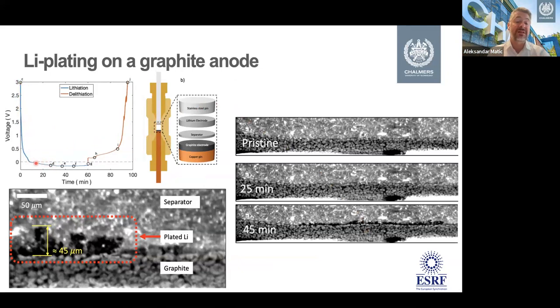So first we put lithium into the graphite, or as you would see, even plate lithium, and then we take it out. So here you have the pristine cell, and you can see up here we have the separator. Down here we have a current collector, and here are the graphite particles, all these round small things. These are the graphite particles where we would like the lithium to be.